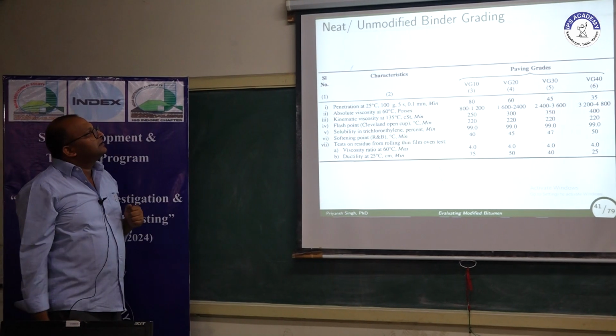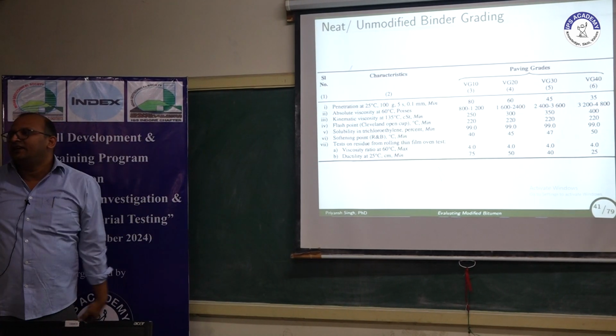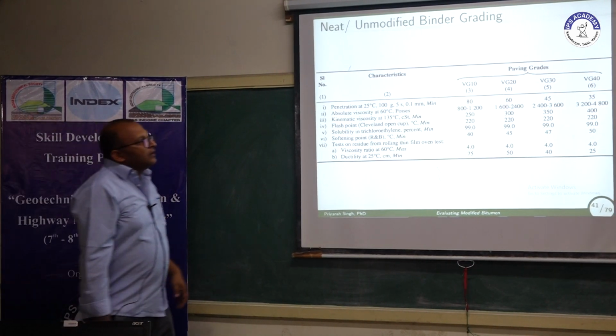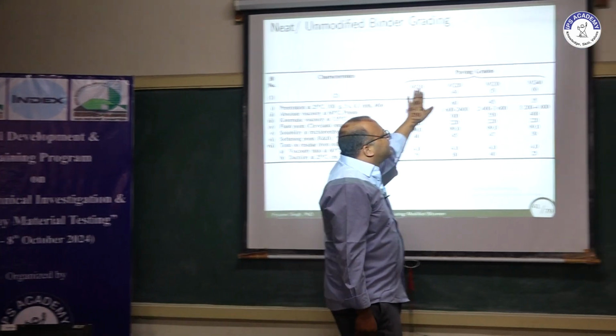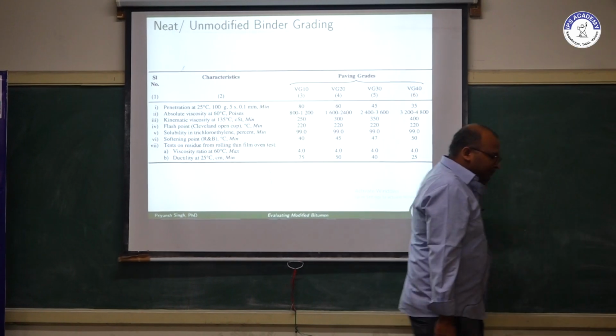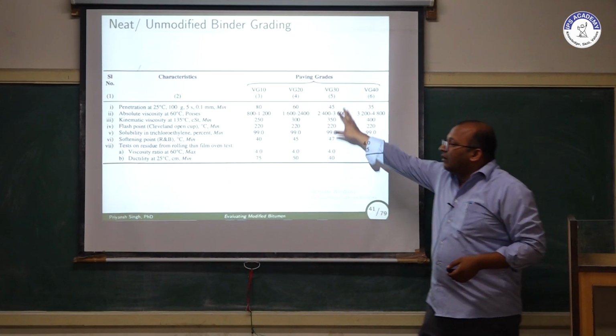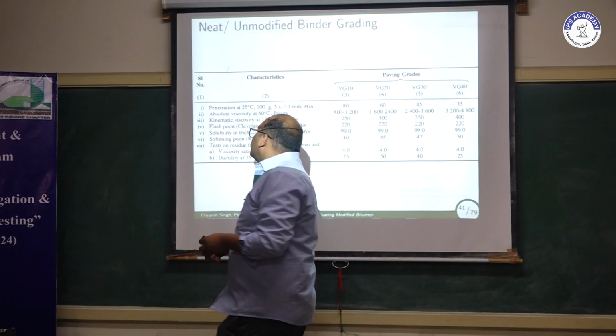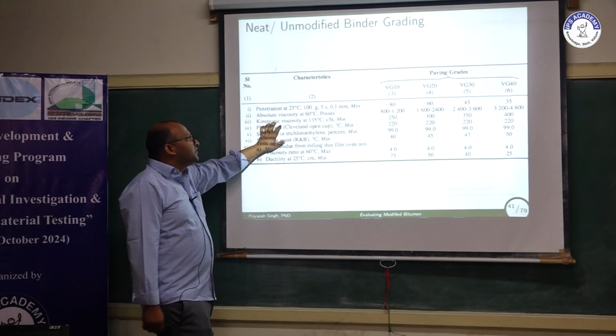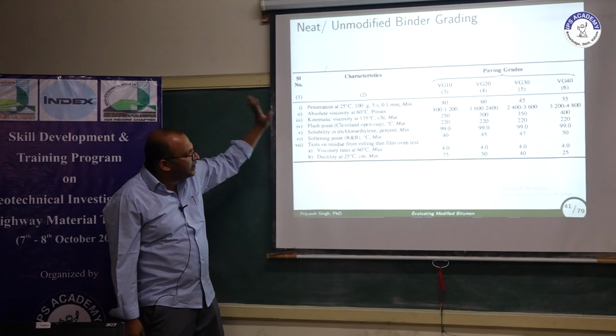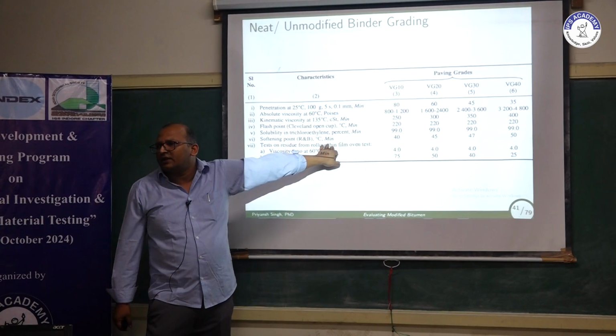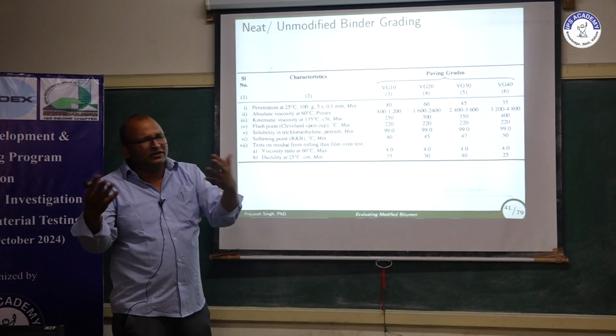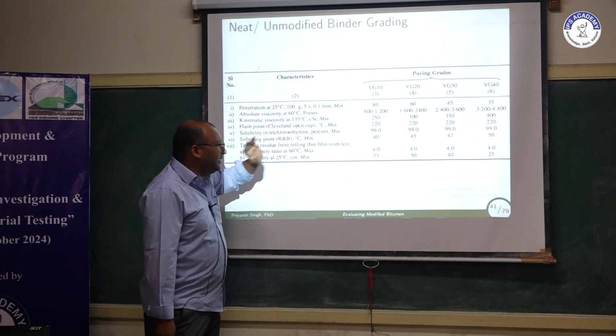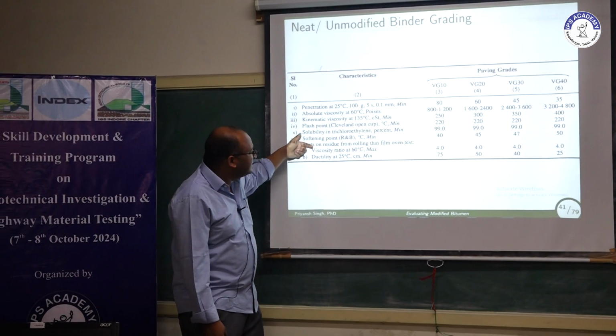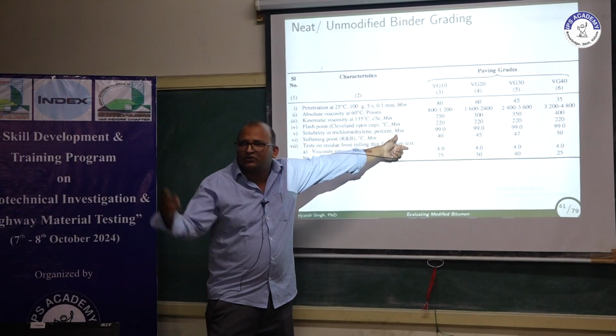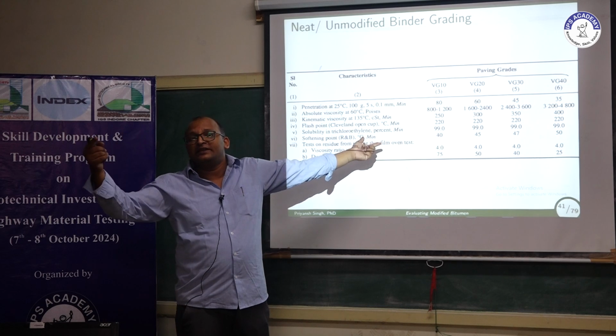Based on these tests, the IS 73 code is being formulated. You can see the 4 different codes: VG10, VG20, 30, 40. All the properties that we have discussed: the penetration, absolute viscosity, kinematic viscosity, flash point, solubility test in trichloroethylene, that means how much purity it is, then the softening point, and then you can see here the test on the rolling thin film oven that I told you, the short term aging.